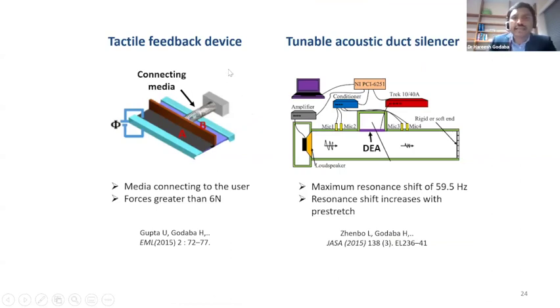Yeah, and further from there, this is to show that we can also utilize this type of dielectric elastomer actuators for high frequency applications. So here in this left side figure, we studied the dynamics of this type of system, and we figured that we can develop a tactile feedback device that can generate forces greater than 6 Newton at more than 100 Hertz frequency. For this, we also did some tests and found that the media that connects, so here we have the dielectric elastomer actuator with a mass that vibrates, and then this is an elastic media that connects this to the user here. The stiffness of this media is very important for what type of output forces this device can generate.